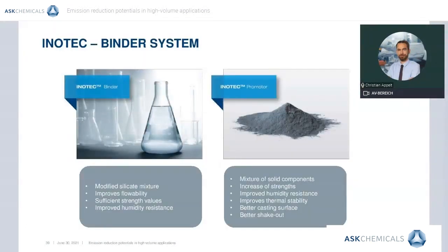The Inotec technology is described as a two-component binder system. Component 1 forms the liquid Inotec binder, which can be described as a modified solution of alkali silicates. The binder has a strong influence on specific properties of the molding mixture, for example flowability, and the sand core itself. Characteristic strength profiles with adjustable humidity resistance properties result in dependency of the type of product used.